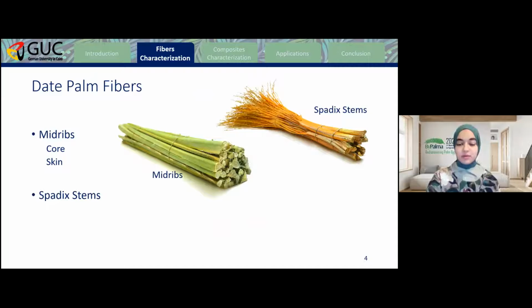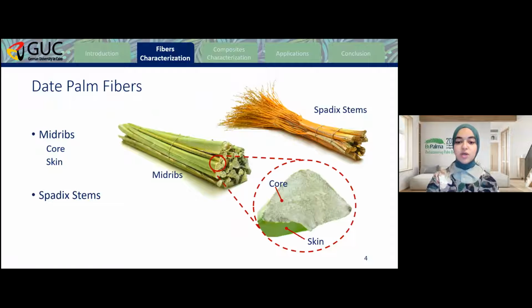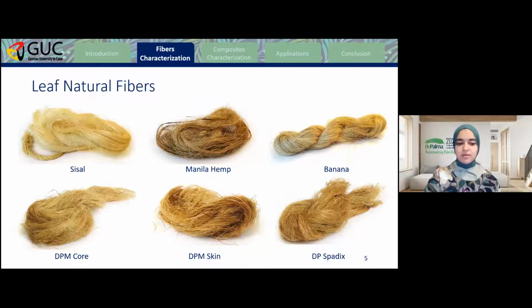So starting with the fibers characterization. In this work, 3 types of date palm fibers were extracted: midribs and Spadix stem, and from the midribs we extracted 2 different fibers, the core and skin fibers. And as mentioned earlier, we compared the date palm midrib core fibers, the date palm midrib skin fibers, and the date palm Spadix stem fibers to other 3 leaf natural fibers: sisal, manila hemp, which is sometimes referred to also as abaca, and banana fibers. We specifically chose those 3 fibers due to the visual similarity between them. When inspected, the sisal fibers look like the date palm midrib core fibers, the manila hemp is similar to the date palm midrib skin fibers, and the banana fibers are similar to the Spadix fibers.